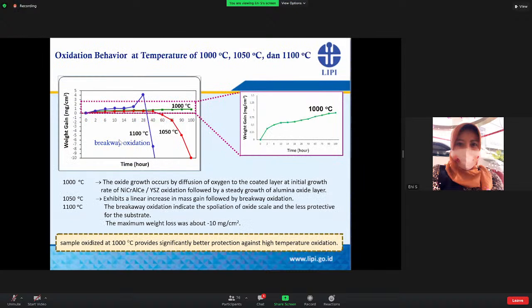This figure shows the oxidation kinetic curve of the samples coated with NiCrAlCe and yttria stabilized zirconia, oxidized at 1000, 1050, and 1100 degrees C. The oxide growth occurs by diffusion of oxygen into the coated layer, and the sample follows the parabolic rate law, which occurs only for the sample oxidized at 1000 degrees C. On the contrary, the oxidation kinetic of the samples oxidized at 1050 and 1100 degrees C